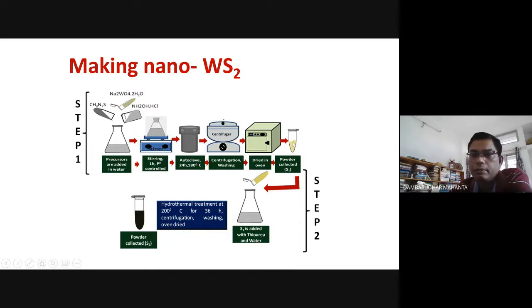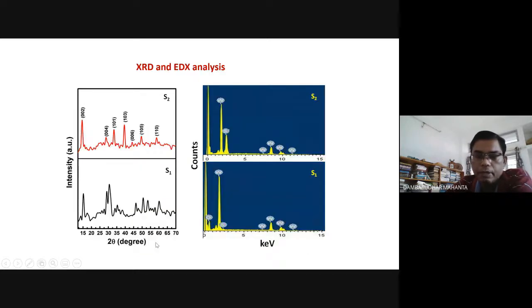dry, you collect a powder, let us say S1, and then add thiourea and water, and repeat this process, subjected to hydrothermal treatment at about 200 degrees centigrade for 36 hours or so, followed by these processes. So we obtain another powder. In this case, we see W and S elemental detection. As you know, EDX is energy dispersive X-ray analysis, in which we first verify whether these elements are present or not. And the left hand side is the XRD pattern through which we determine the crystal structure.